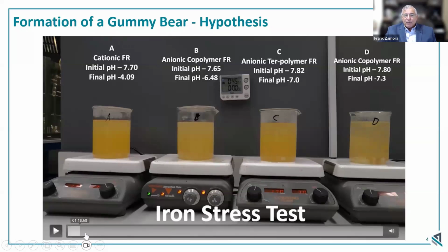So let's go through a little bit of a time span here and take it through an eight-hour period, at which point we basically shut the test at 8 hours. So after 8 hours, you can see that this acrylate has already agglomerated completely out of solution. So basically we have a nice clear fluid simply because all the polymer has basically fallen out and agglomerated down here in the bottom. What you're seeing over here in this other copolymer is done basically the same thing.